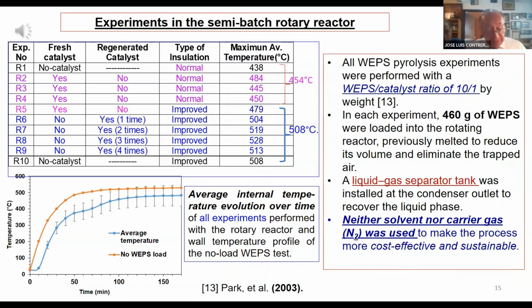Four experiments with fresh catalyst and four experiments with regenerated catalyst are shown in the table. The experiments with normal heating are shown in purple, with an average temperature of 454 Celsius, and experiments with enhanced heating in blue, at an average temperature of 508 Celsius. The profile of temperatures against time, with load and without a load of waste, is also shown.